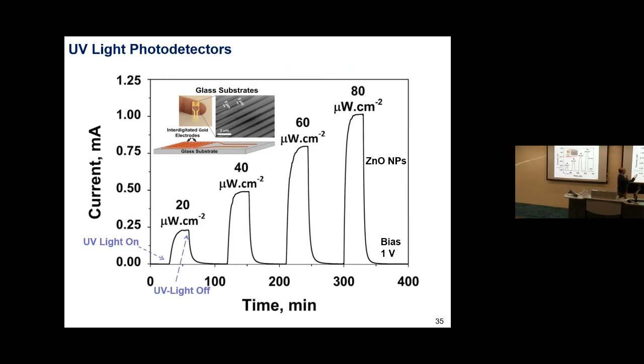And that's what we did. It's a very simple measurement, like the one I showed you before - we measure the current at a certain voltage. Once you put the UV light on, you see that the current increases, and not just a little bit - it increases by orders of magnitude, actually 7 orders of magnitude. This enables you to work at very low voltage and detect UV light very accurately.